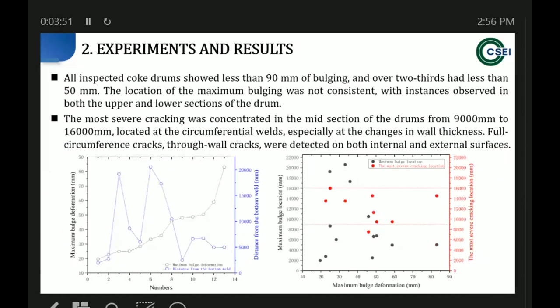So we analyzed the data, and we can see all coke drums show less than 90 millimeters of bulging, and over 2/3 of them less than 50 millimeters. And we can see the location. Some of them are at the top of the drum, and some of them are located at the bottom section of the drum, so it is not consistent.